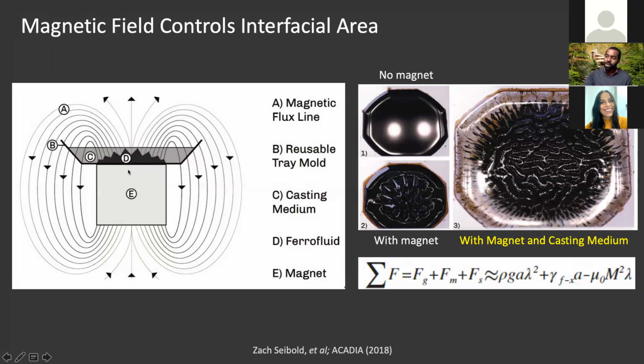So just a different schematic, done in a slightly different way. We have the magnet here below in E, the ferrofluid in D, and now we're starting to add this casting fluid. This casting fluid is immiscible, and you notice that even with the same magnetic field, you go from spikes into labyrinths. This can be explained by looking at this factor down here, which is the surface tension, which is what we talked about in the previous case. Instead of it being ferrofluid and air as in the spikes case, it would be ferrofluid and the casting fluid.